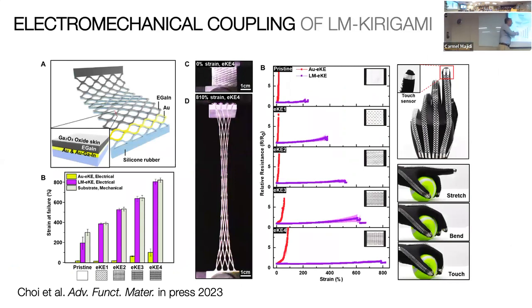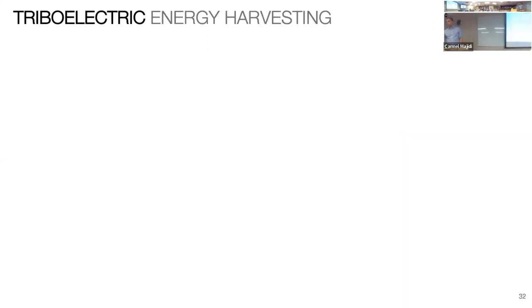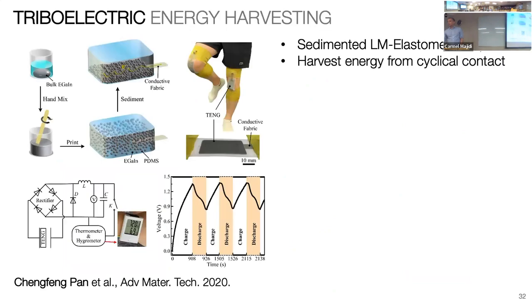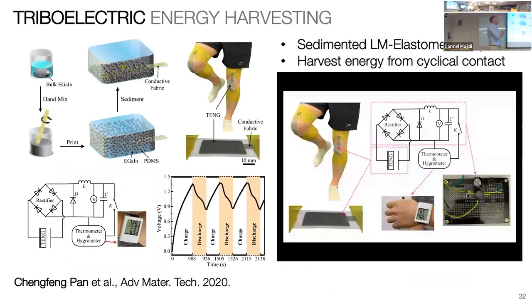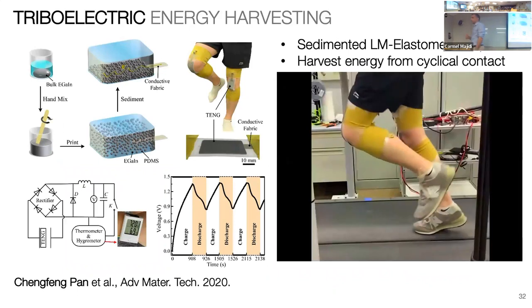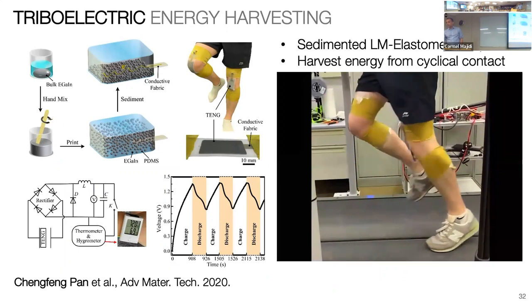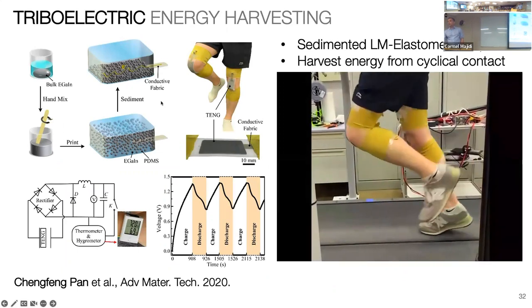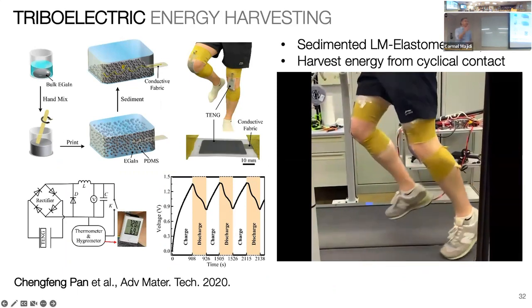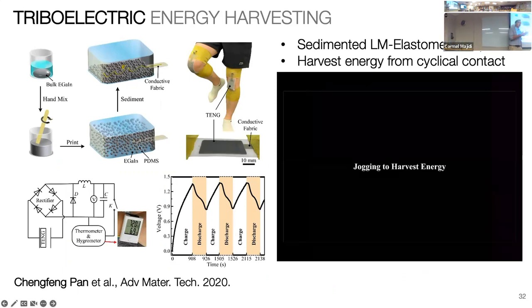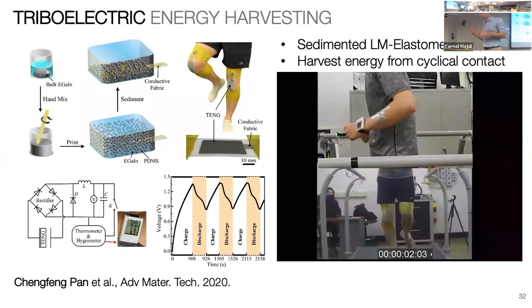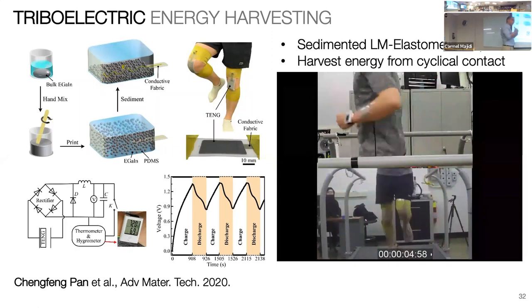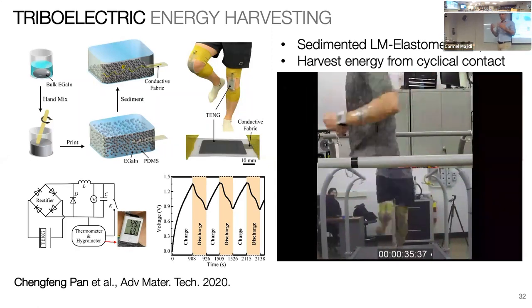Here's another version of that, where to make these even more stretchable, up to 1,000% strain, we can introduce these kirigami patterns, cut splits through them. And again, why this is significant from a wearables standpoint is that now we can look at other energy harvesting modalities. Here's an example of triboelectric energy harvesting using these conductive liquid metal rubber composites. We're using these as pads that come in repeated contact with the skin, say during an activity like jogging, and that produces triboelectric charge.